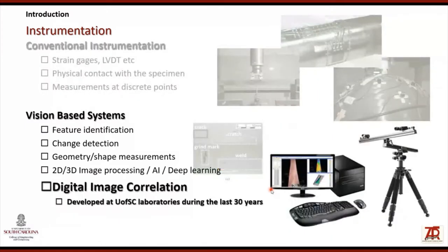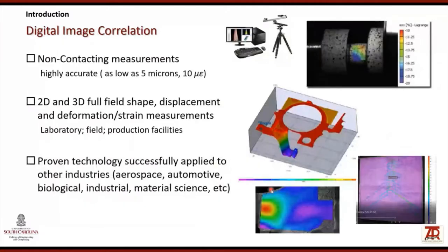This technology — digital image correlation — is the one we will focus on in today's presentation. DIC techniques have been developed at the University of South Carolina Laboratories during the last 30 years, with well-established procedures that have also moved into commercial applications. It's a non-contacting measurement technique, highly accurate, capable of measuring deformations with resolution as low as 5 microns and strains to 10 microstrain.